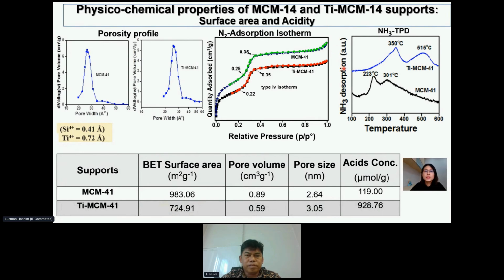Okay, so for the acidity study, we're using the TPD with ammonia gas, okay, and this indicates that the modified MCM shows a higher concentration of the acid sites as compared to the pure MCM41 support. And this reveals the favorable role of these titanium species, where it really helps to improve the acidic properties of the overall silica support.